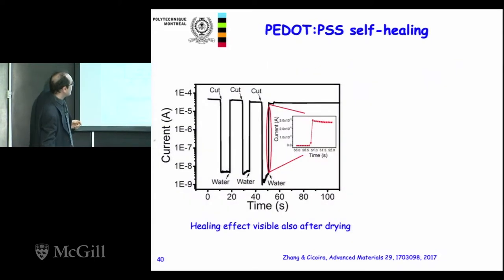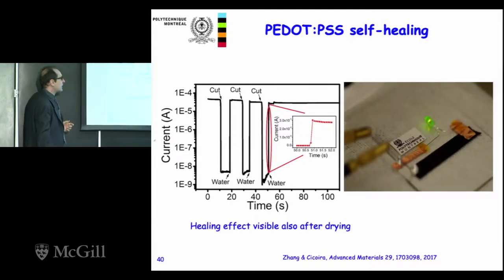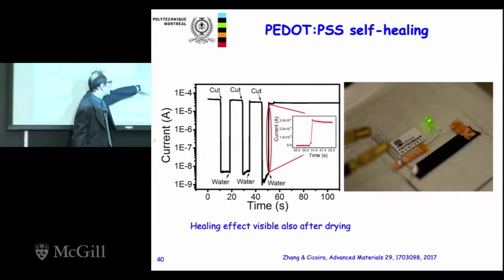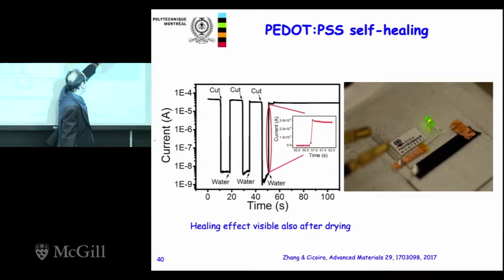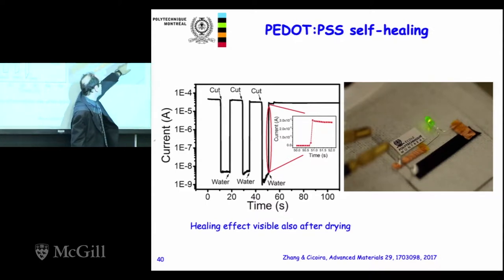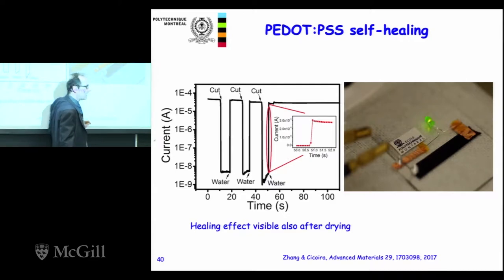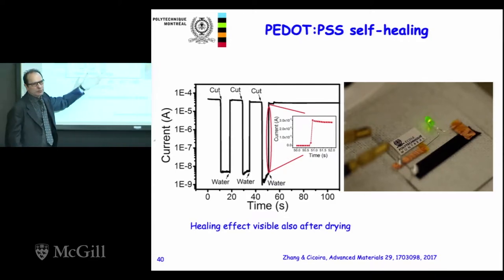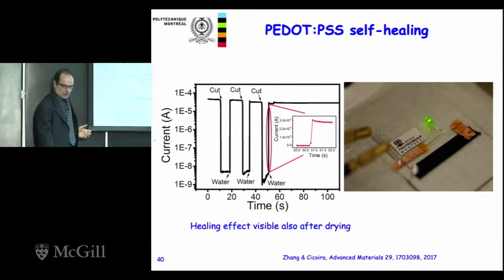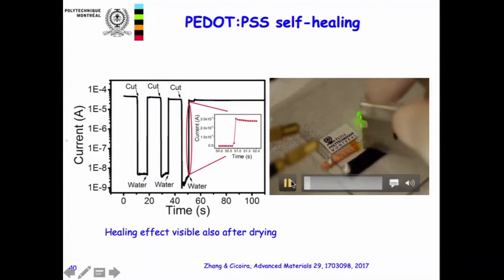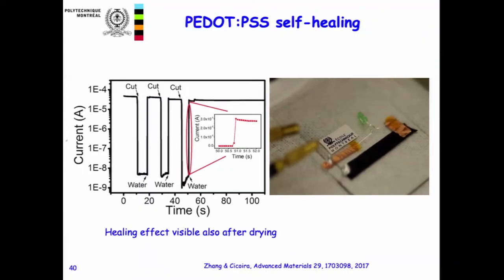And then naturally, we performed the experiment, which is actually very nice. So we did a very simple experiment. We made a small circuit. So you have an LED here, which is powered by a battery or a power supply. And part of the circuit is a quite thick PEDOT:PSS film. The thickness is about 5 microns. And you can see here what happens. The film is there. Then we cut the film with a blade. And of course, the current is interrupted.